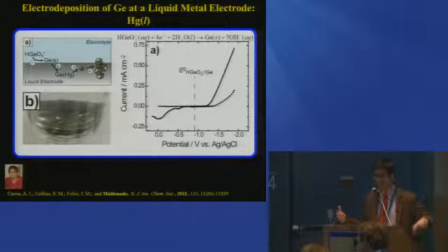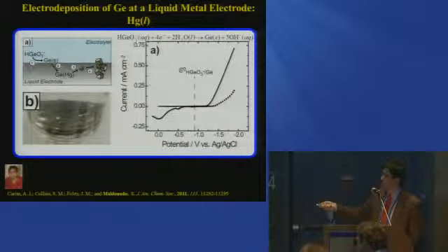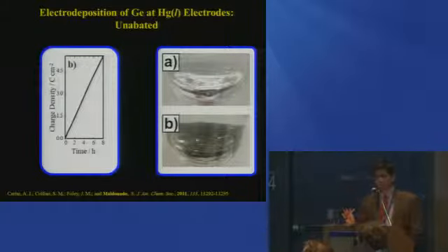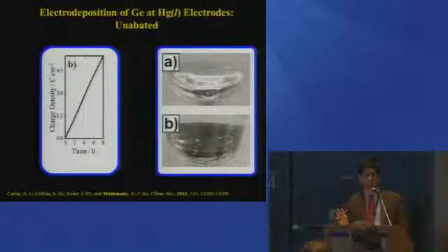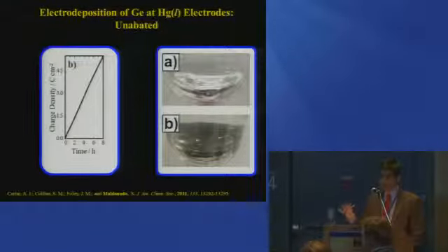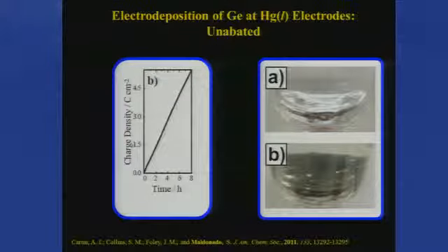You do this electrode experiment after a few minutes by biasing your electrode somewhere out here. What you see is that your nice clean electrode becomes basically scuffed over with a bunch of dark brown soot. The interesting thing is this dark brown soot is elemental germanium, which in and of itself is kind of interesting, because if you do this experiment with a solid gold or platinum or standard electrode, you don't get much of any solid deposit. This whole process passivates after a few monolayers. But on liquid mercury, you can just let your electrodeposition process go all day if you want, and you get more and more dark brown stuff.